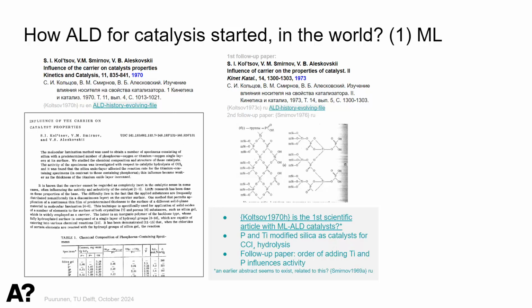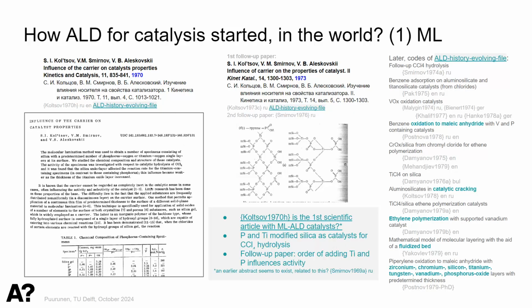If someone has told you that these were not cited because they were all in Russian, this is from 1970 and it is in English. So that's not only Russian. There are follow-up papers for this, and I have been looking at our ALD history evolving file to find these because you don't find them cited in reviews. And I found 15 publications. So in addition to carbon tetrachloride hydrolysis, there was oxidation of benzene and something else to maleic anhydride. There are polymerization catalysts, also chromium on silica, and catalytic cracking. So quite a lot. And then also fluidized bed modeling, maybe the first significant modeling paper on ALD.